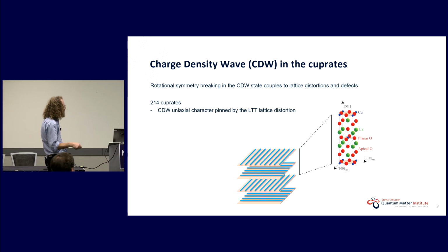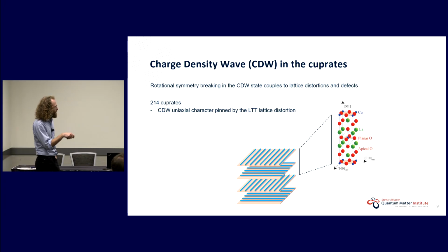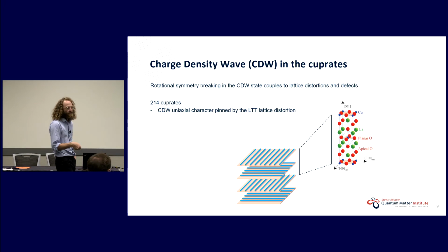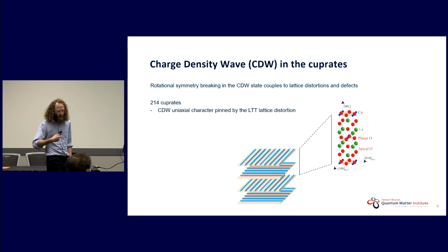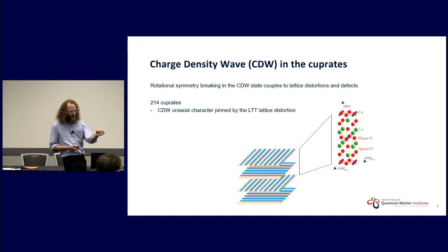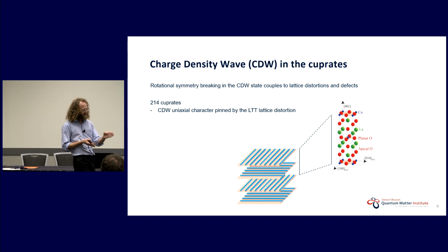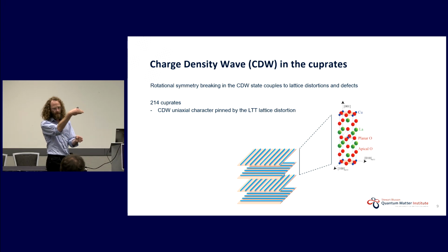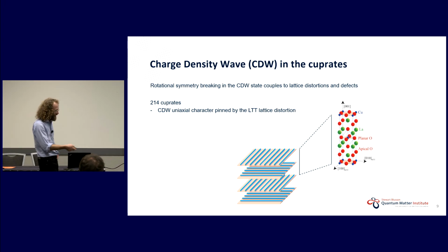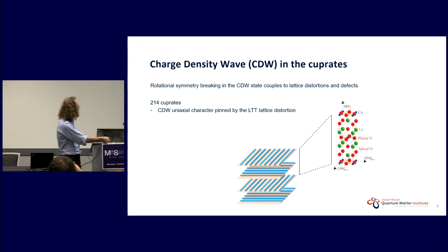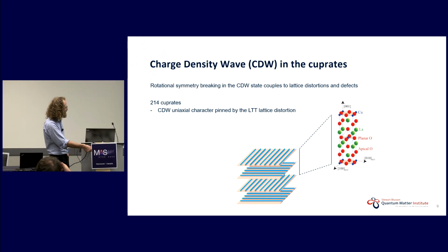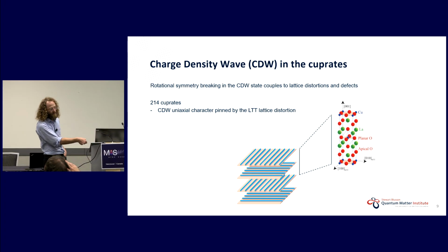So our focus will be the 214 cuprates. Here you have this special phenomenon that there's this low temperature tetragonal distortion. This is a structural distortion which is uniaxial in the copper-oxygen planes, but this uniaxial character alternates from one plane to the next. And this can be taken advantage of because it basically gives you a periodicity along the out-of-plane direction, a periodicity associated with this uniaxial character.